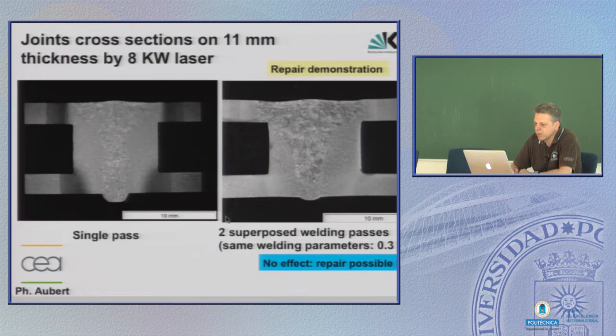These are 11 millimeters thick, to produce this weld without destroying these delicate cooling channels internally. Sometimes, if something is happening during the process, you have to recurve welds, which requires then a second or even a third welding pass. They have done this here intentionally and welded the same structure a second time.